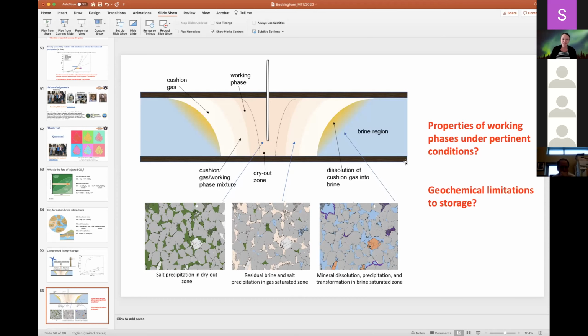What we've seen in some other systems, in terms of what's actually going to precipitate, might be amorphous, but understanding where the reactions will occur is still a large uncertainty. In some of my PhD work, I looked at the Hanford site and we had amorphous silica precipitating on the grain surfaces, on all of the surfaces. But it's really closely tied to coupling between the flow and reaction, which is a complicated problem. So we don't actually know where those reactions are going to occur.